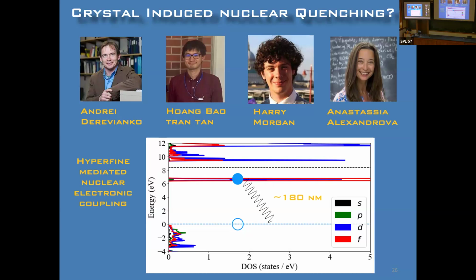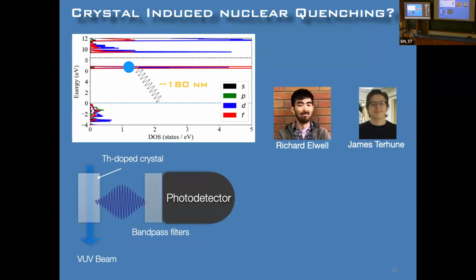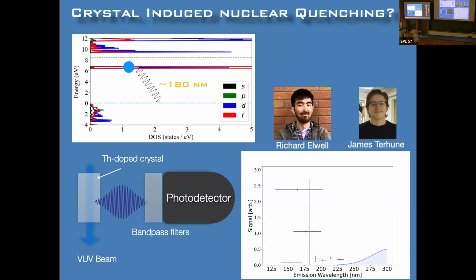So we said, okay, if this is true, we should be seeing this redshifted fluorescence from the crystal. So we went off to look at that. There was not a lot of signal, so Ricky and James used every filter we had and did some massive Gaussian deconvolution. The spectrum they reconstructed is shown in blue. Red of 225 nanometers, we see some broad background that we knew was there already. You can see that because the crystal does glow a little bit because there's radioactivity inside of it. We had measured that, and it glows around there. So it was nice that they saw that.